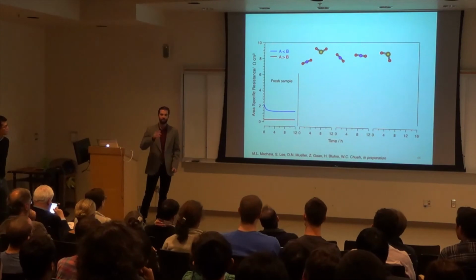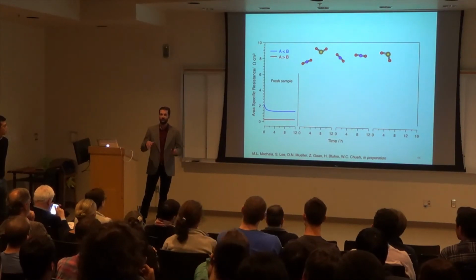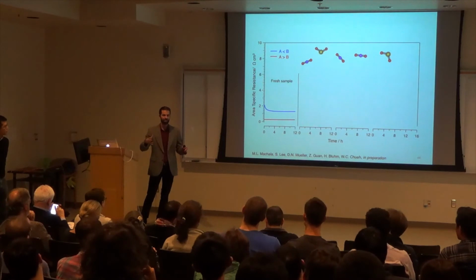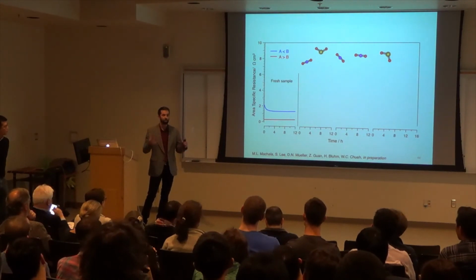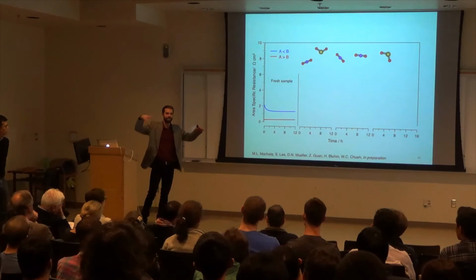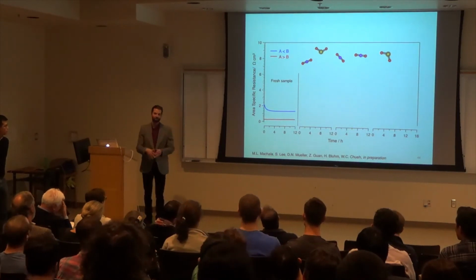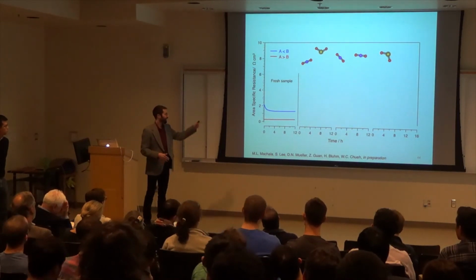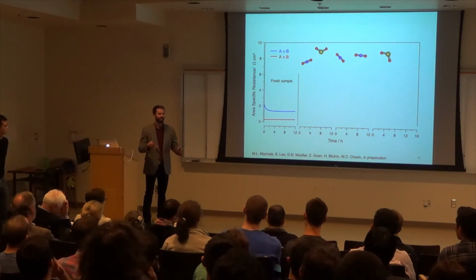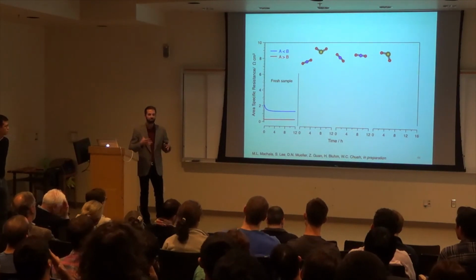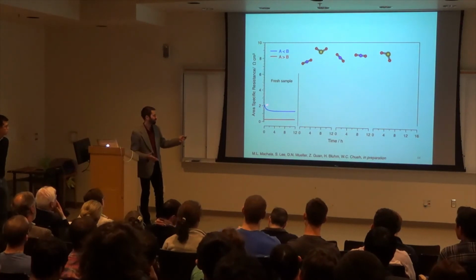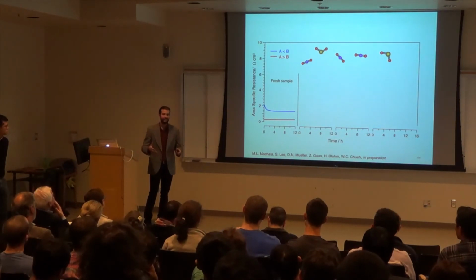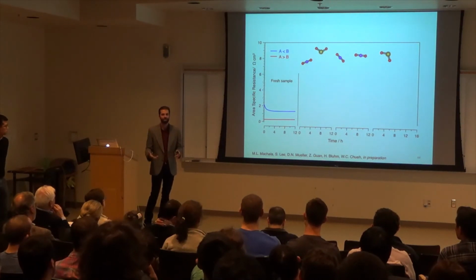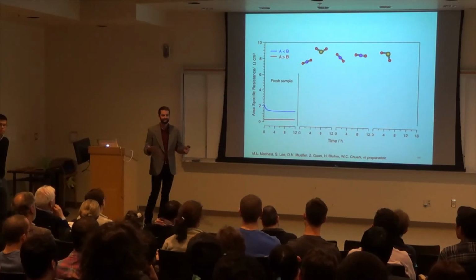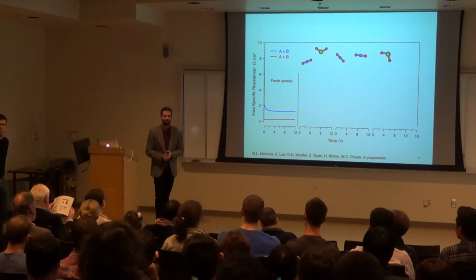So you can imagine that these films are deposited in a very low oxygen environment. So they actually have a lot of oxygen vacancies. And when you heat them up in, say, 21% oxygen air, the oxygen actually equilibrates and comes back into the film. And so at the same time that the oxygen is coming into the film, the cations are going to react. So the cations are relatively dynamic compared to the oxygen. And so what this is basically showing you is that the surface is slowly moving to its thermodynamic state, but it's not happening very quickly. And that's kind of what we understand right now, but it's definitely something we want to investigate.